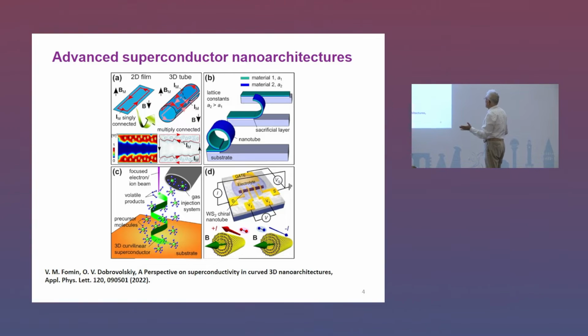If you etch off this sacrificial layer from a side of this structure, then these two films, which can be a few monolayers thick, are under significant strain because of mismatch of their crystal lattices. And this strain should be somehow realized, and it is realized in deformations. There can be different deformations, but under certain conditions, this deformation is rolling.